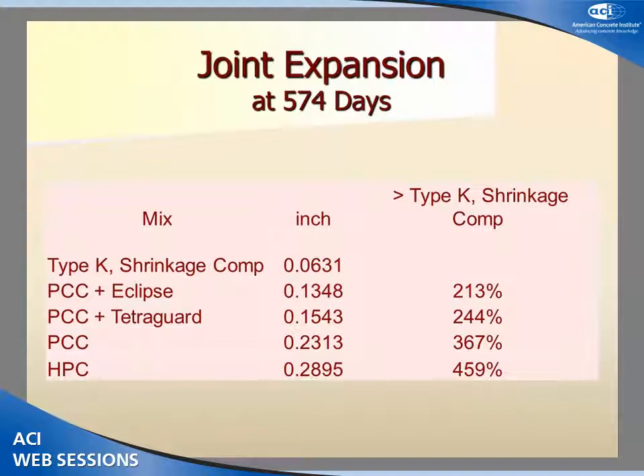Here I brought the table for joint expansion from the graphs that I already showed you. After 574 days, you can see all the expansion for all of the concrete we used are greater than type K. For example, Eclipse showed a joint expansion about 2 times greater than type K, and Tetraguard showed about 2.5 times greater than type K, and Portland cement showed about 3.5 times larger joint expansion compared to type K, and high performance concrete showed about 4.5 times larger joint expansion than type K.